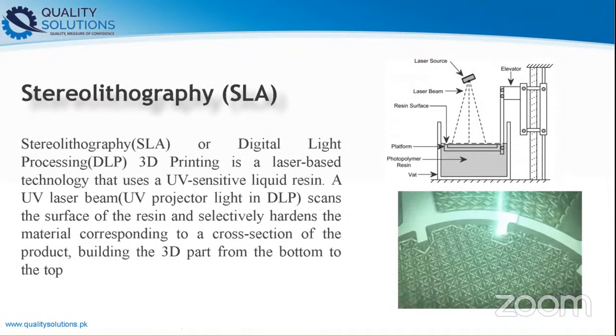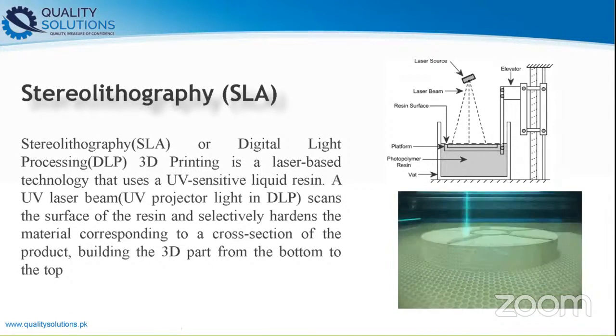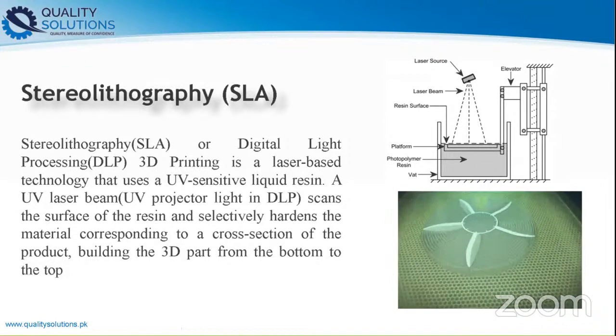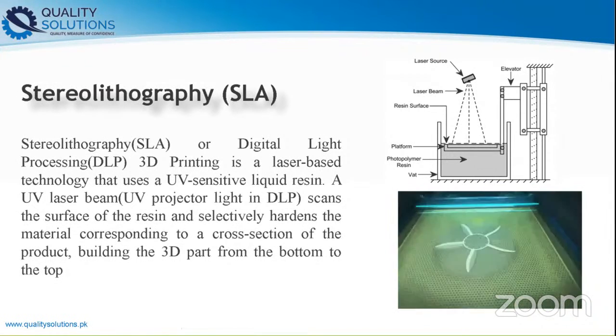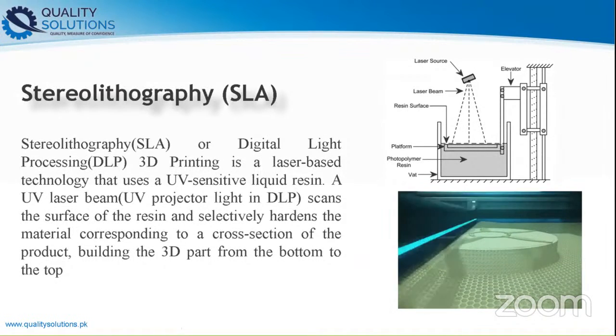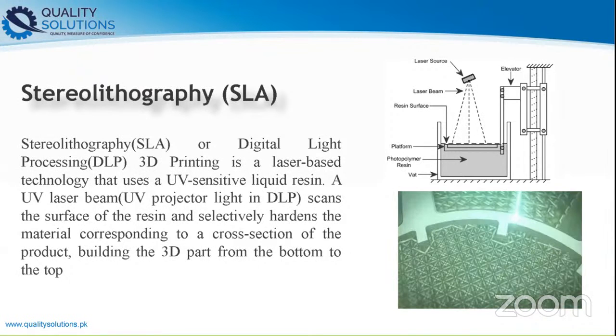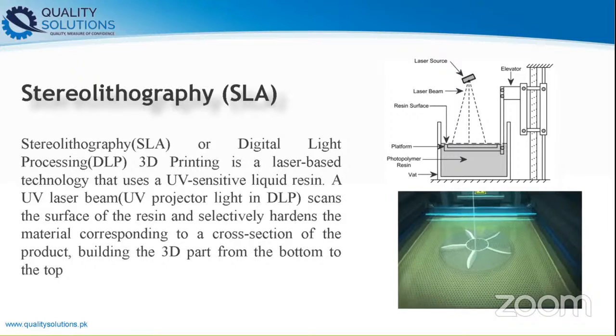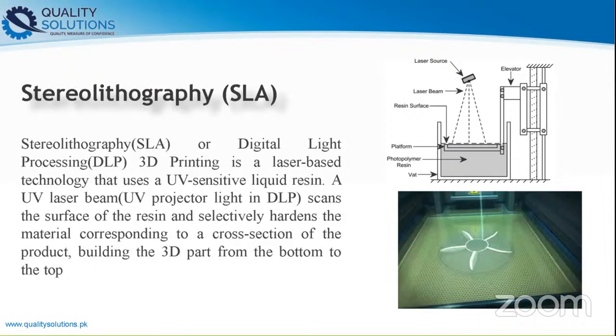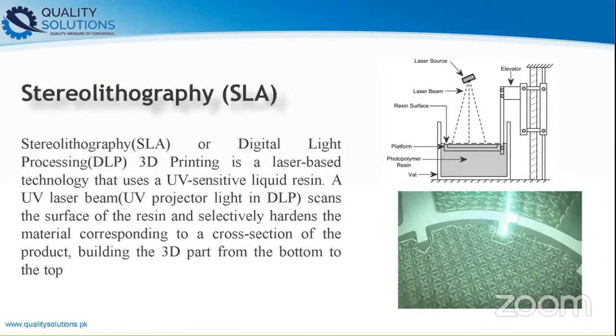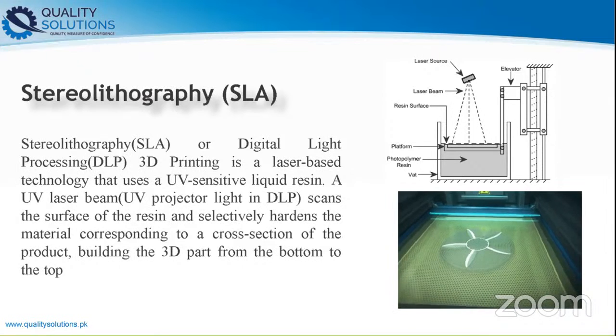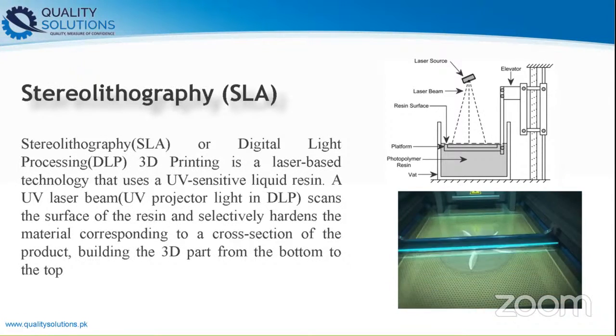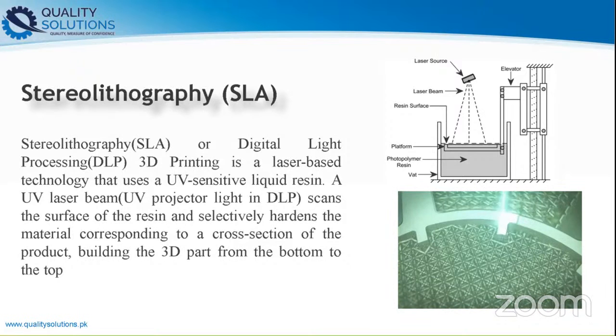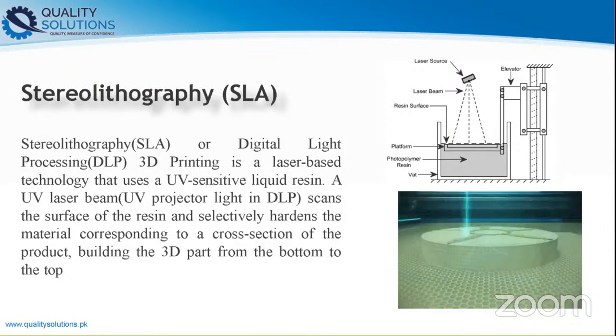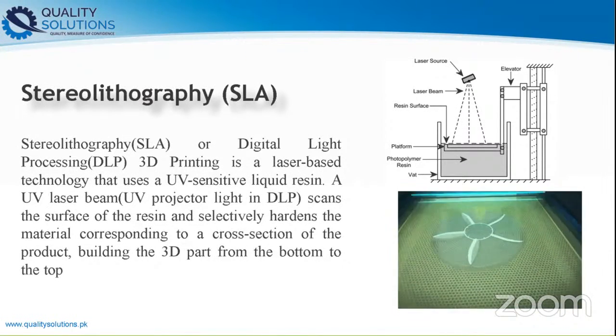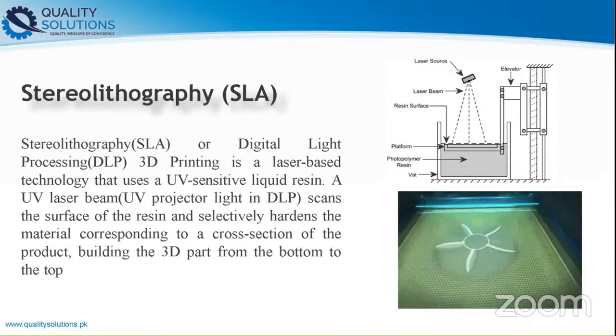The SLA printers use a laser to UV cure specific areas of a resin tank to form a solid part, one cross section at a time. These cured areas, however, are not at full strength until post processing with UV. Because of this, and the angle and orientations that SLA parts are typically printed at, sagging of unsupported spans can occur. As one layer is built up at a time, this effect becomes cumulative, leading to the dimensional discrepancies sometimes seen in tall SLA parts.